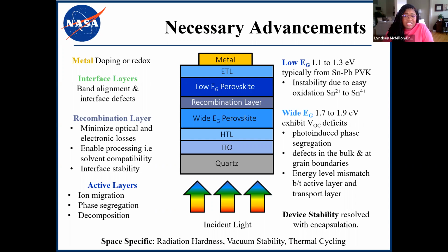The active layers of these devices can sometimes fall prey to ion migration and phase segregation and environmental induced decomposition, like some of the things we've been talking about today. Particularly when you break down these junctions, the low band gap bottom cells are based on a mixed tin halide perovskite or another material like silicon or CIGS. And when the low band gap material is a perovskite, it's typically tin films which suffer from instability due to easy oxidation of the tin. And this can result in a shortened device durability and poor stability. Now, in the case of the wider band gap cells, these are usually achieved by substituting bromide for iodide in iodide-based perovskites, and that higher bromide content will widen the band gap, but then those suffer from defects and photo-induced phase segregation.